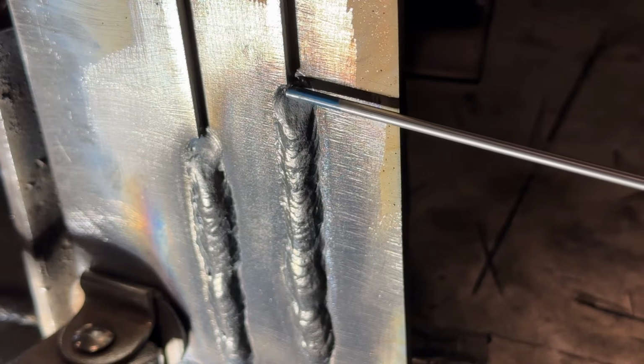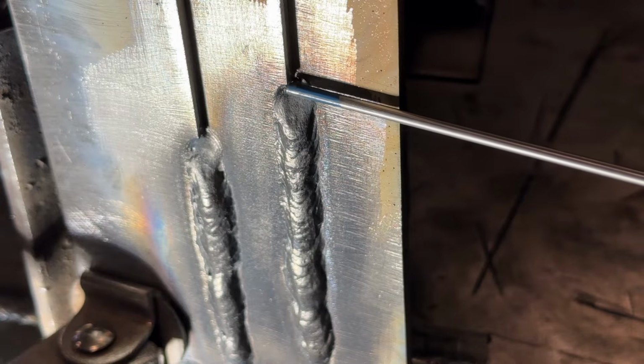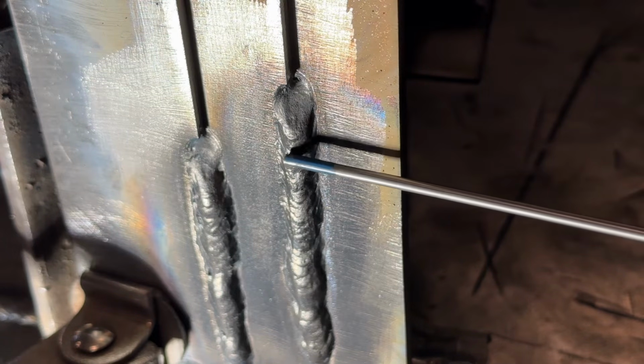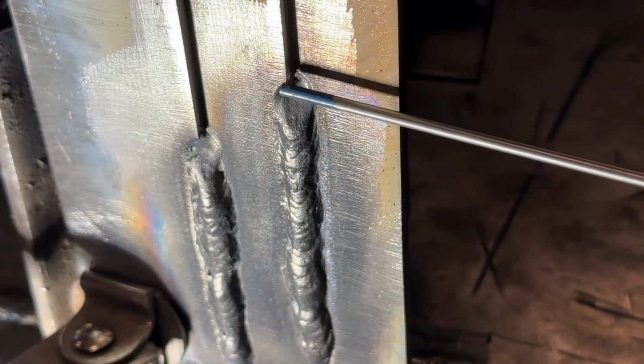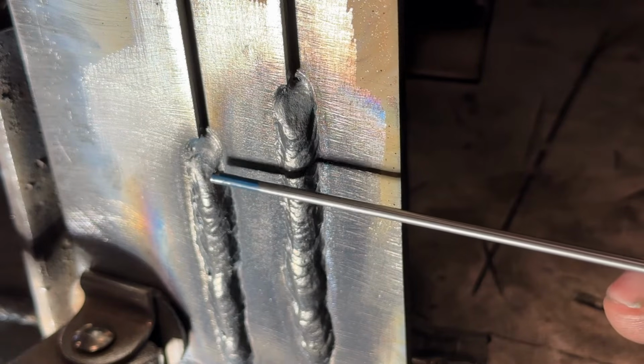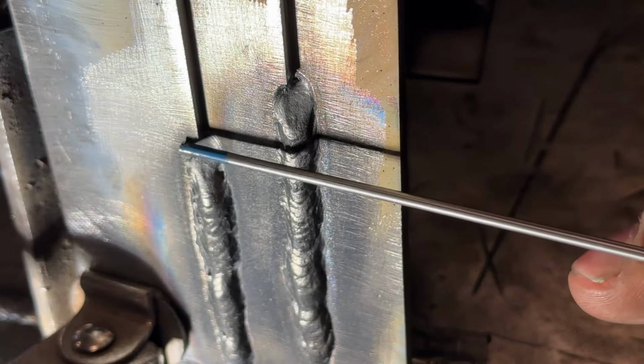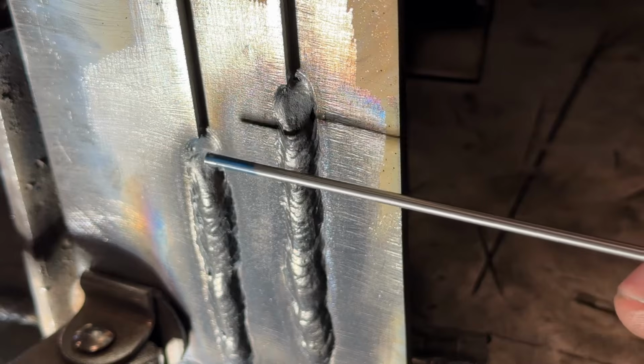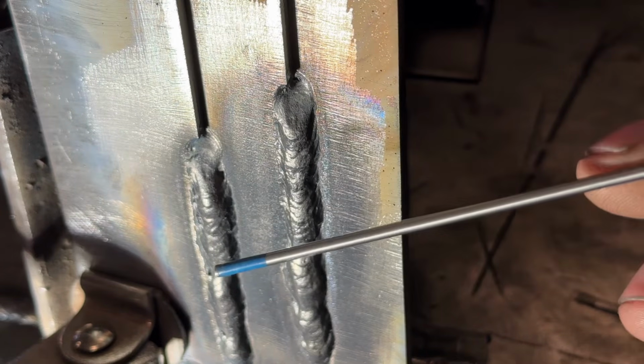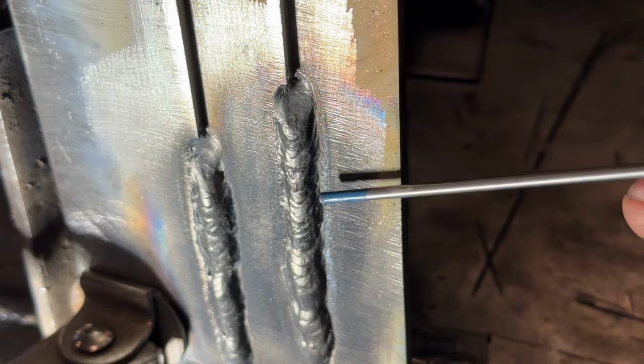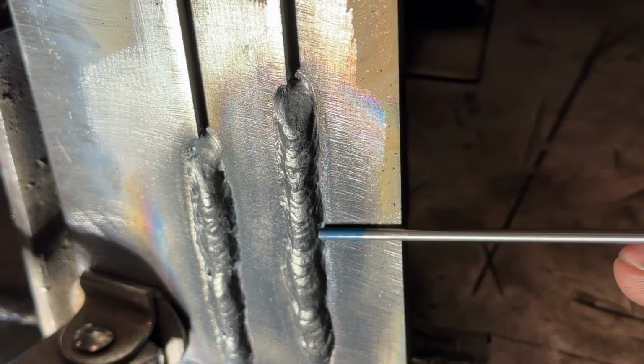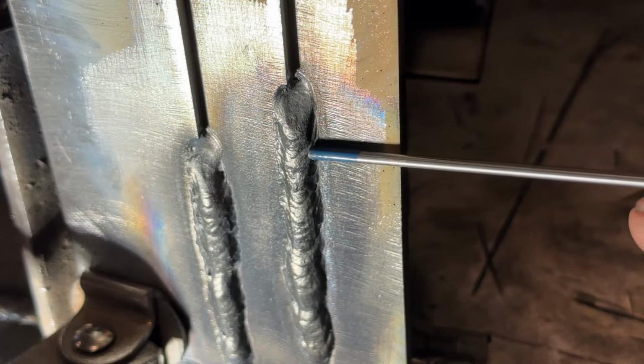Now this looks worse than it is because that's where I stopped, but our melt over, if you look down here, is about right, just a millimeter over the edge. When you look at this, it's actually melted far more over, and that's due to the increased heat, due to the increased wire feed speed. But yeah, this point up is exactly what we want to be aiming for.